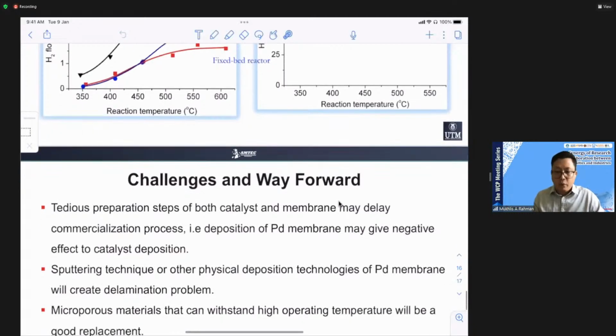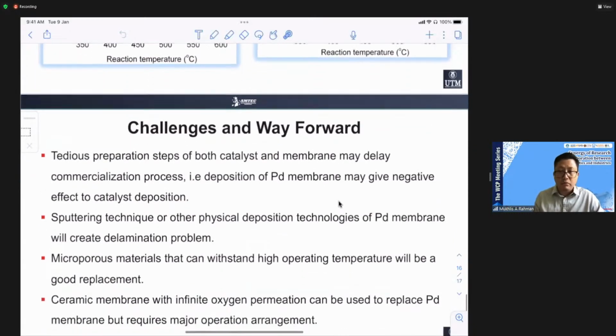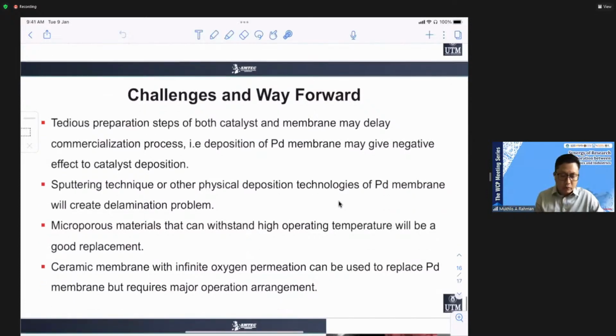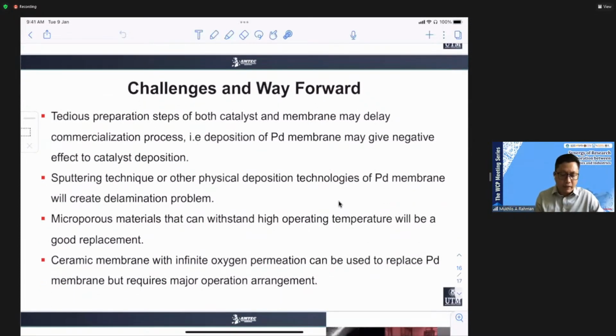So now we come to the challenge and way forward of this work. Actually, to tell you the truth, both systems have a tedious preparation step, both catalyst and membrane, and this will affect the commercialization process because the deposition of the palladium membrane actually has a negative effect on the catalyst deposition, because the chemical reaction used in the palladium membrane will dissolve back that catalyst. The sputtering technique seemed to be very good, but because of the physical deposition, it creates delamination problems.